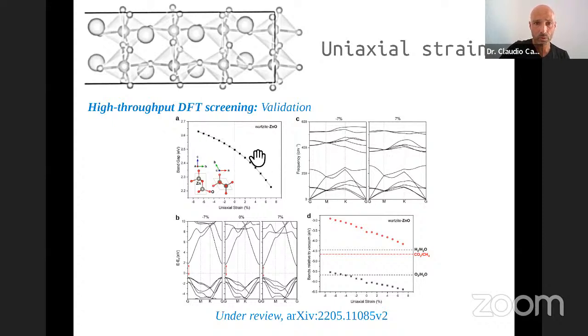So here in both sides of zinc oxide, we have a monotonous tendency of the energy band gap under increasing uniaxial strain. We can understand this decrease here in terms of band degeneracy lifting, or band splitting, as induced by symmetry breaking.